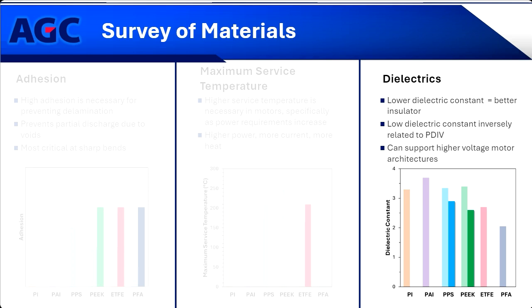So again, I want to highlight our ability to improve materials and improve their properties for a specific application. And I show here that we have been able to decrease the dielectric constant through, again, polymer modification or compounding. We can improve the dielectric constant by making it lower for the PPS and the PEEK. So we have lowered these almost to, and in some cases even past, the level of ETFE.